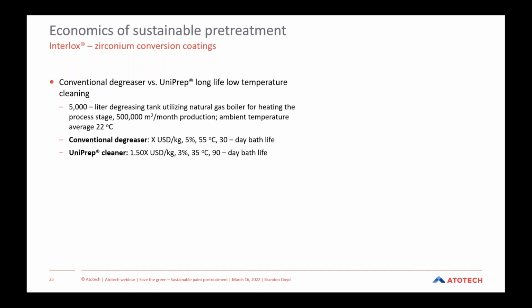You can see with a conventional degreaser, we consider a cost of X US dollars per kg with operating parameters of 55 degrees Celsius at 5% concentration and a 30-day bath life. With the Uniprep cleaner, we consider that the cost will be about 1.5 times higher, but we're able to achieve lower operating concentration, at 3%, lower operating temperature at 35 degrees Celsius, and an extended solution life of 90 days.